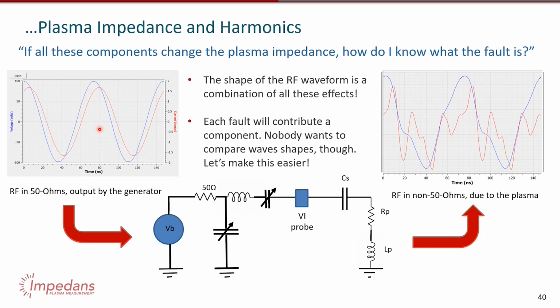Okay, and then this was real data measured in this. I had a VI probe in the 50 ohm side and a VI probe in a non-50 ohm side, and this is what the data looked like. You can see there's a distortion in the voltage wave and a massive distortion in the current wave. This is all to do with this nonlinear load, this complex circuit.